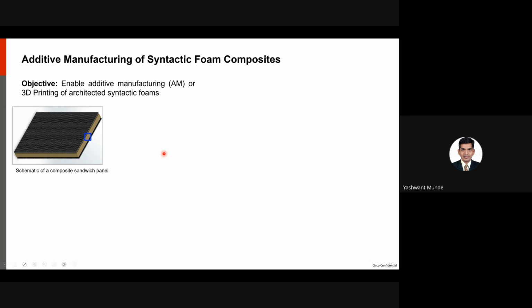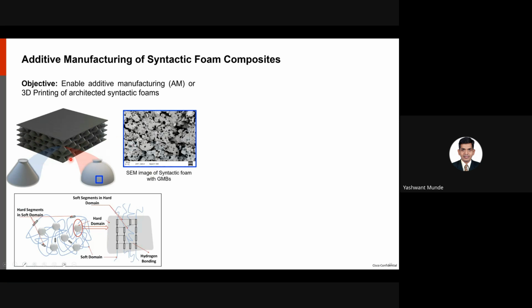Now, the objective here is to enable additive manufacturing or 3D printing of architected syntactic foams for these sandwich cores. Here's the idea. We touched upon this part, which is architecting at the millimeter length scales. Now we want to introduce an additional level of hierarchy by creating segregated matrix regions in these walls of the unit cells with embedded particles within them. The material, which is in this case a thermoplastic polyurethane, TPU, inherently is a composite at the nanoscale, where they have hard domains which are arranged hard structures as shown here, which are hydrogen bonded, and they're surrounded by more flexible chains of polyols as shown here.